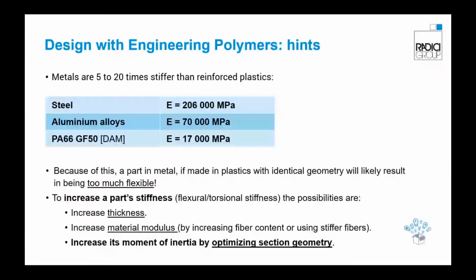We say that the metals are 5 to 20 times stiffer than reinforced plastics. As we can see from this table, the elastic modulus of the steel is quite higher compared to the modulus of polyamide 6,6 with 50% of glass fiber. Because of this, a part in metal, if made in plastic with identical geometry, will likely result in being too flexible and premature breaks may occur.